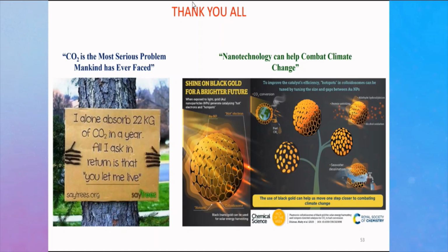Subhajyoti Samanta asks: do you emphasize only CO2 conversion to fuel, or CO2 splitting, reduction of CO2 coupled with steam reforming and chemical looping? Partial oxidation of methane would be more profound to fight against man-made climate change. Yes, it's not ideally a good idea to just think about one reaction, CO2 to methane. CO2 plus water gives me CO plus hydrogen, and I can use CO plus hydrogen to get methane, ethane, methanol. So that syngas synthesis is also possible, and partial oxidation is also possible. The idea is to convert the CO2 which is now thrown into the environment as waste, and use that waste CO2 as your feedstock to make useful chemicals and fuels. Silica is ideally not conducting. It's an insulating material. Obviously, if you create a defect, you will have some defect state.